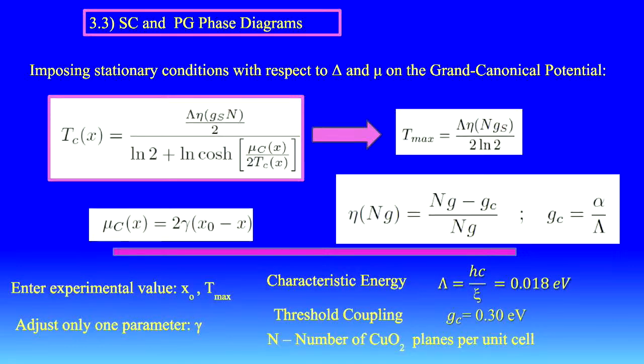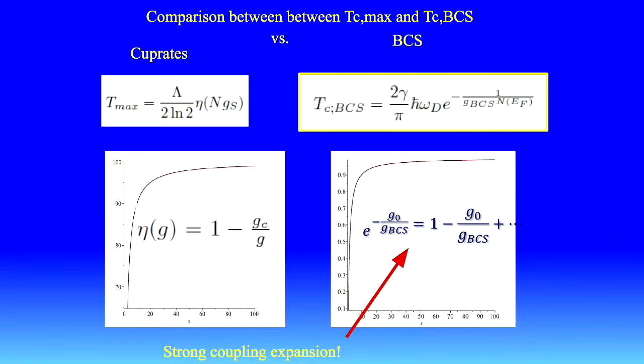Okay. So now if you compare this maximum temperature with the BCS result, you have this BCS, and this is our result. So we have an energy momentum scale. We have there the Debye energy. We have this eta function, which is depicted here. We have this exponential function, which is depicted here. And this eta is given by this. You see that if we expand this in the strong coupling, it gives exactly the same result. So it's very suggestive that we obtain this expression for it.